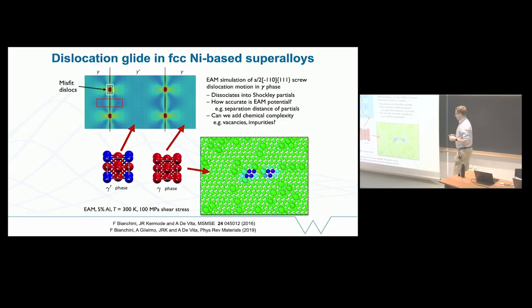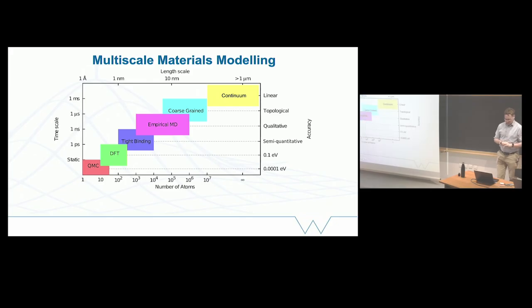In an FCC material, dislocations dissociate into partials, so they're not just pure dislocations, they separate, and they have a stacking fault in between them. I'll explain why that is important when thinking about the potentials in a minute. But you can see we have these two halves, the dislocation here, they're moving around dynamically. And what we could maybe observe experimentally, we could take a thin slice of this material, we could put it into a TEM, transmission electron microscope, we could actually see the separation, and we could measure experimentally what this distance is. That's the kind of thing we could use to validate our approach. However, getting a quantity like that right relies on a really careful calibration of your model. We'll come back to that shortly.